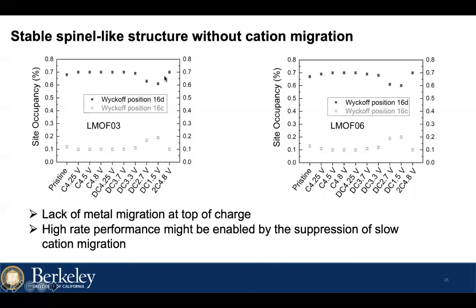In other lithium-rich materials, oxygen redox almost always couples with cation migration, which is slow. But in our material, the manganese migration is so limited, even at the top of the charge, where the oxygen redox is heavily used. So this might be the reason that the high rate capability can coexist with the oxygen redox. And we believe the oxygen redox is not intrinsically slow, but the cation migration is.